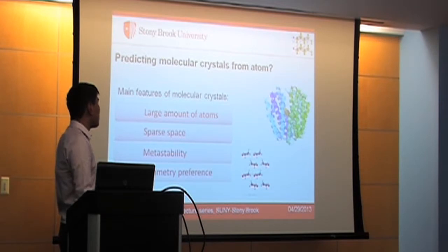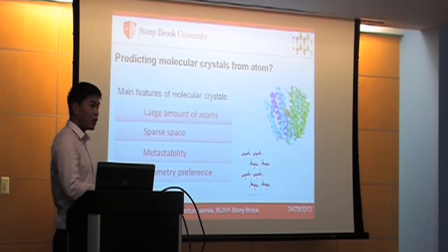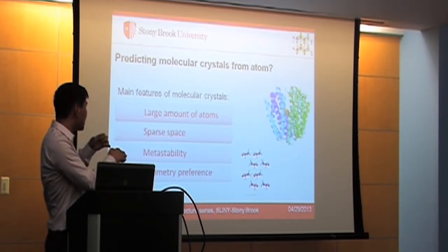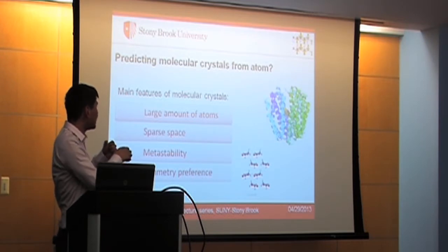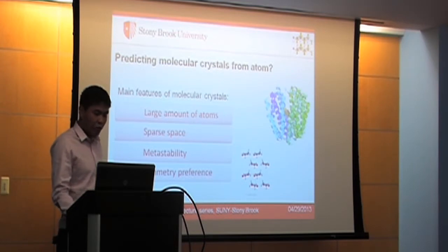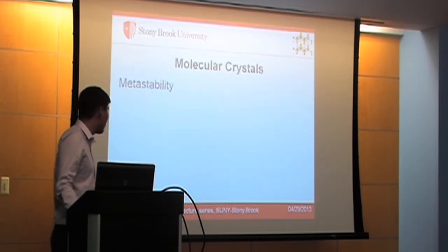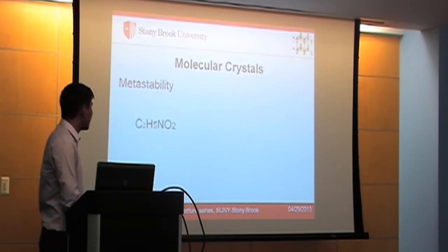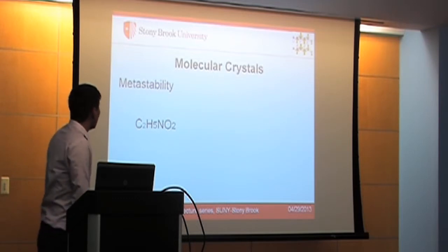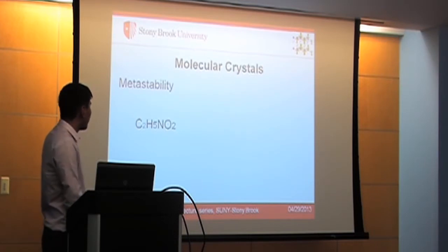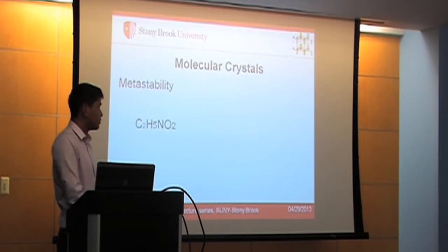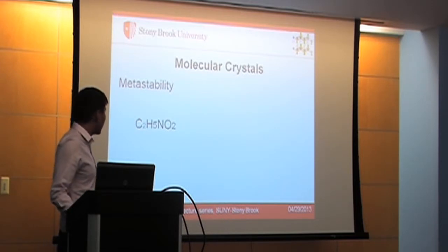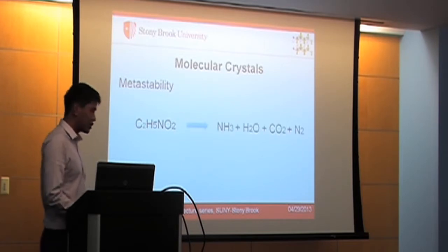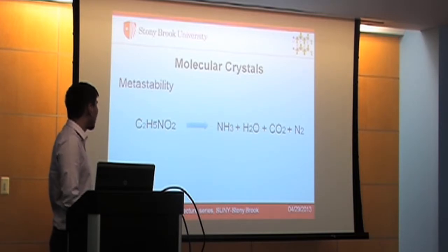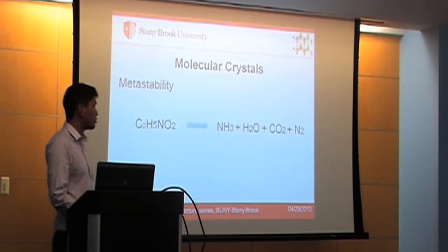Firstly, usually molecular crystals contain many atoms, and the molecules have very big interaction, so that the unit cell usually contains a lot of empty space. And another important feature is that many organic compounds are actually metastable. By metastable, it means that by energy, they are not the ground state. So if we take a chemical compound like C2H5NO2, which is actually a type of amino acid, the basic origin of our life, and if we do prediction for this particular chemical system, we found that the ground state is not the structure based on the molecular form of amino acid, but a mixture of small molecules.